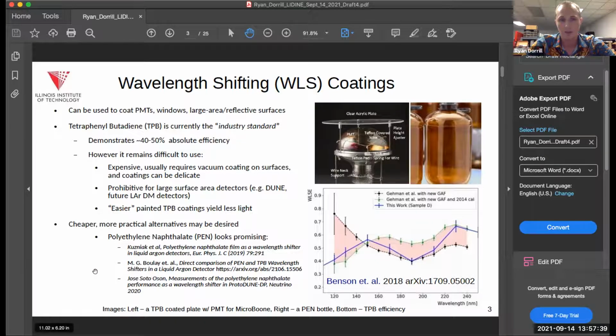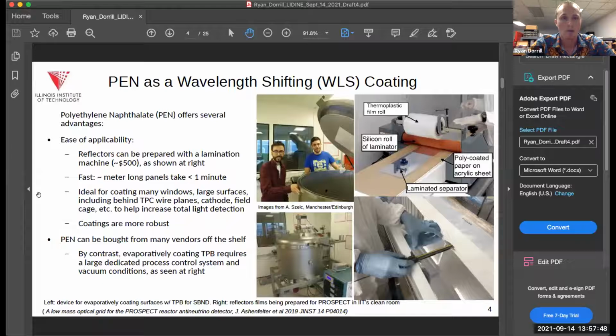And there are a bunch of papers about this, including some recent talks and results. I included some of those in the back here, where you can read more about it. So the advantages to PEN, which is essentially very close to common plastic, are it's easy to use and get a hold of. The reflectors can be prepared with a lamination machine, which costs about $500. And you can see an example of that on the right there. We have one here in the lab at IIT. Whereas TPB, as I mentioned, is coated evaporatively and you need a big machine like those here on the left.